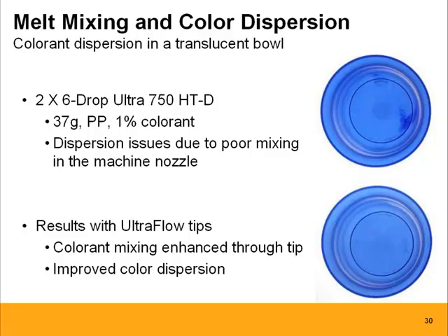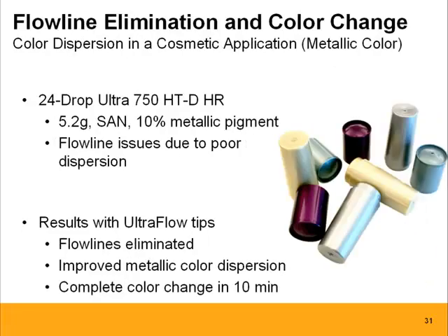The other thing, especially with pearlescent, remember I mentioned in the beginning, some of these effect colorants tend to come in larger chunks, in larger pieces, and especially the rectangular ones that have a real shape to the pigments, they have a tendency whenever they get split in a melt stream or not properly prepared, they pretty quickly concentrate and then give off different colors. And what we can do here too is by dispersing it, for example, with an UltraFlow or doing it properly in the screw and barrel, we can achieve better results and also faster color change by properly mixing the colorant into the polymer matrix. Very important.